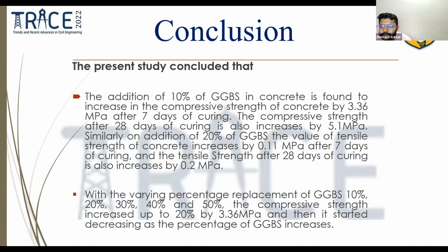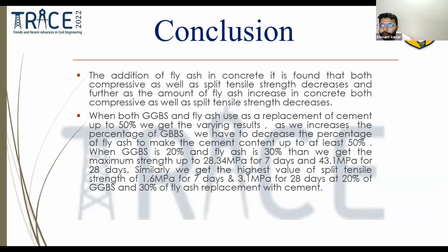With the varying percentage replacement of GGBS, 10%, 20%, 30, 40, and 50%, the compressive strength increases up to 20% by 3.36 megapascal, and then it starts decreasing as the percentage of GGBS increases. With the addition of fly ash in concrete, it is found that both compressive as well as split tensile strength decrease, and further as the amount of fly ash increases in concrete, both compressive as well as split tensile strength keep decreasing.